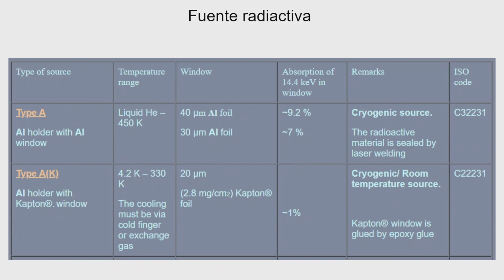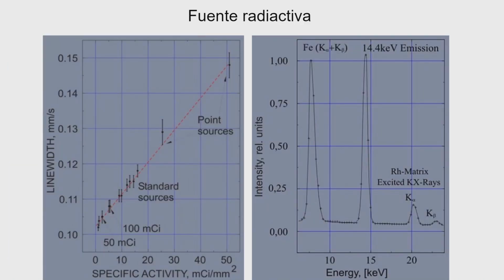Well, here there are some types of sources with aluminum window, with kapton window, for instance, and they are appropriate for certain conditions of operation. Okay. And as I say, we try to buy sources of 50 millicurie because it's useful for us. It gives us enough time between the need to replace the source. But as you see, if the activity of the source increases, the line width increases too, because then you need to have more cobalt-57 in the rhodium matrix, and the probability of interactions between the cobalt emitters increases.